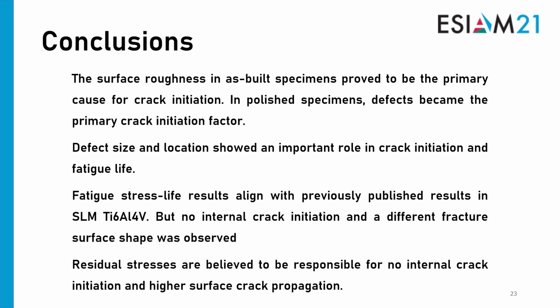Now, when comparing the stress life results with previously published results in SLM titanium Ti6Al4V, we see good alignment, but no internal crack initiation and a different fracture surface shape was observed. The differences were associated with residual stresses, which were believed to be responsible for no internal crack initiation and higher surface crack propagation that has led to a different fracture surface shape. These residual stresses were believed to be present since no treatment was applied, no heat treatment or hot isostatic pressing.